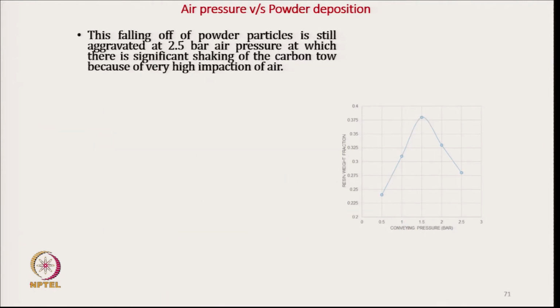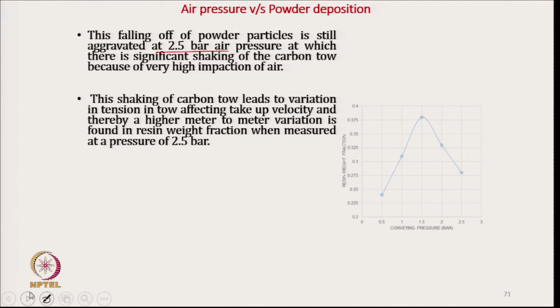The falling off actually continues further above 2.5 bar. So, there will be a shaking action beyond 2.5 bar pressure, so there will be very little resin deposition. Okay.